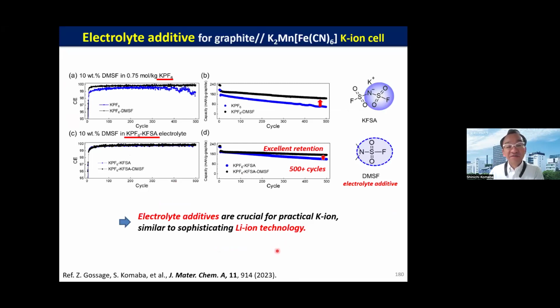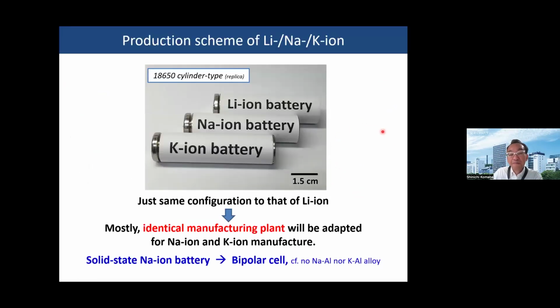As an electrolyte additive, by adding 10% DMSF, and by mixing PF6 and FSA anions, capacity retention is highly improved, and during 500 cycles, capacity is almost maintained constant. There is less and less capacity degradation by adding a small portion of DMSF. Because the cell configuration is just the same as lithium ion, identical manufacturing plants can be adapted for sodium and potassium ion batteries. For solid state batteries, basically lithium ion technology can be applied to sodium and potassium cases.